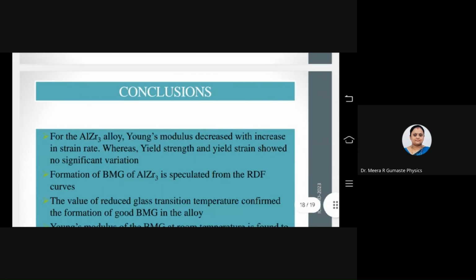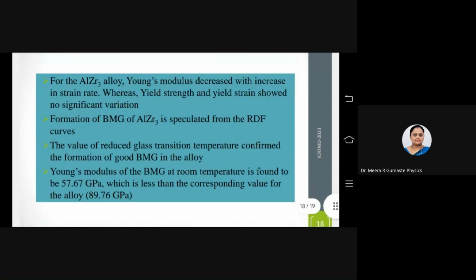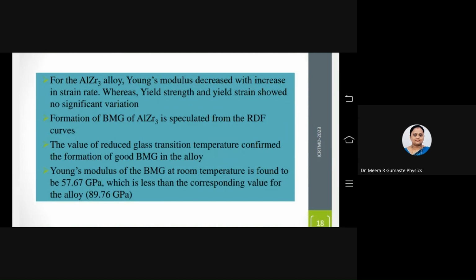And okay, so this comes to the conclusion. So for this AlZr3 alloy, we have seen that Young's modulus decreases with increase in strain rate, whereas yield strength and yield strain showed no significant variation. Formation of bulk metallic glasses of AlZr3 is speculated from the RDF curves, that is the radial distribution function. The value of reduced glass transition temperature confirms the formation of good BMG, and the Young's modulus calculated for this BMG was around 89.76 GPa.